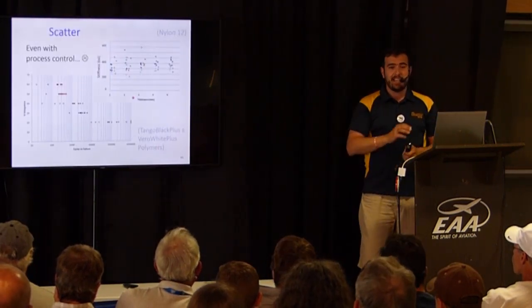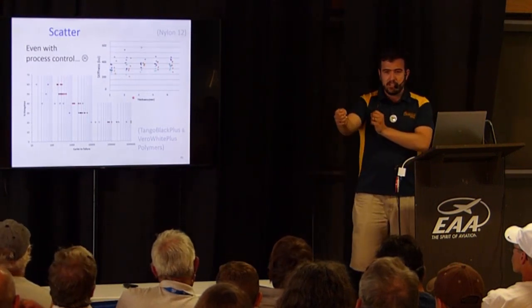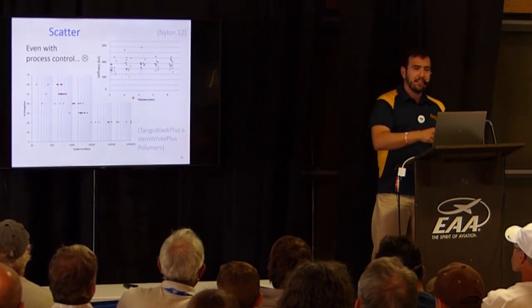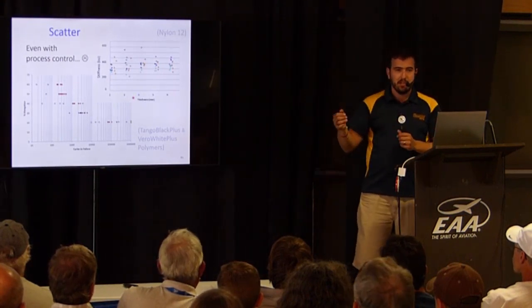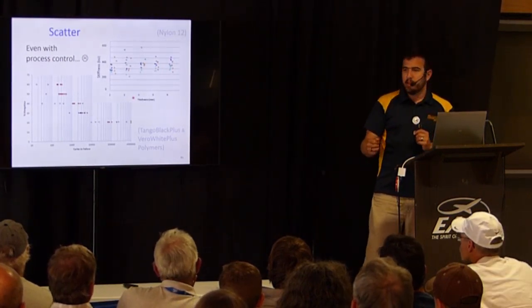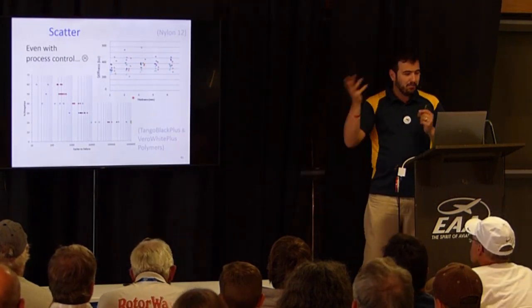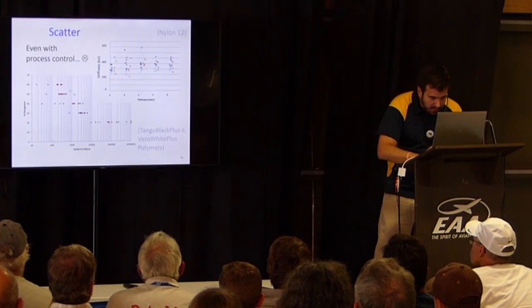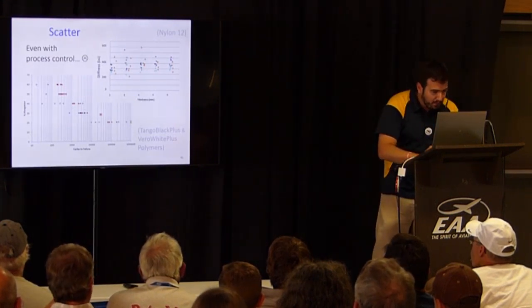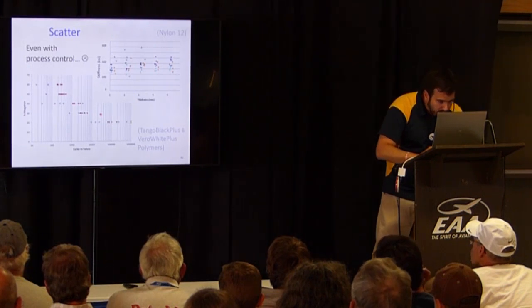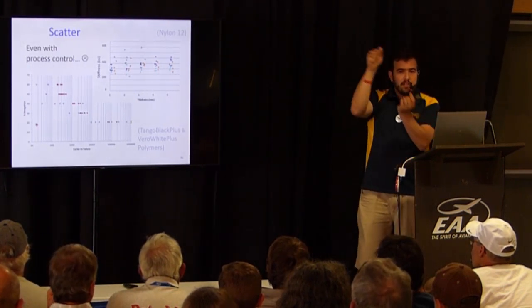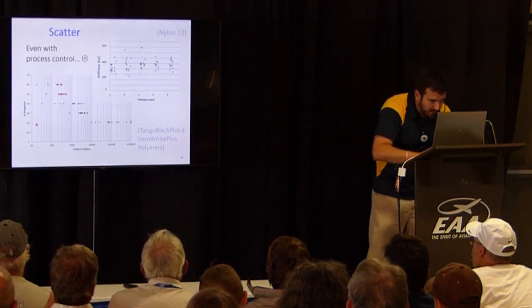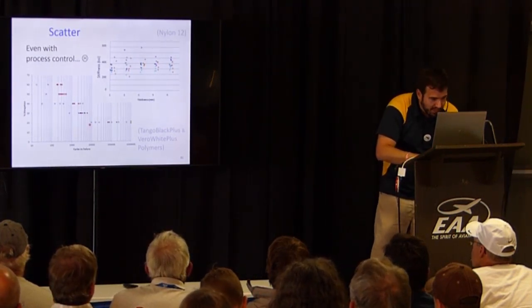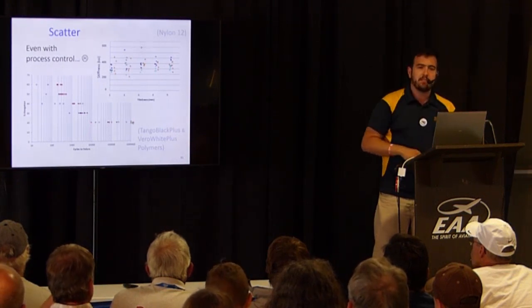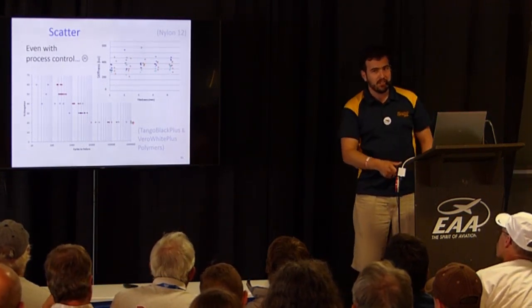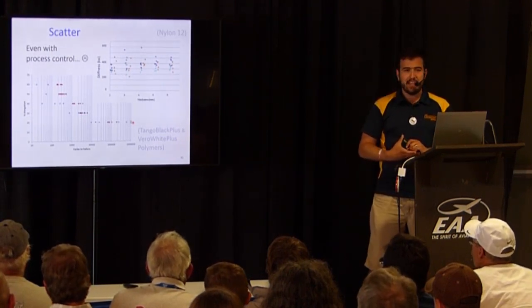Oh, and the scatter. The scatter is huge, right? You 3D print a thing, and you test it, and you get a number, you hear how strong it is or whatever. You try to 3D print another identical thing, and you test it, you get a pretty different number. 3D print a third one, very different number. For example, here they 3D printed a certain combination of polymers, and they did a fatigue test on it. If you elongated 20% during each test cycle, one of the things they 3D printed lasted 10,000 cycles, and another thing they 3D printed lasted 1 million cycles. That's a factor of 100 difference in fatigue life. So the scatter is just out of this world.